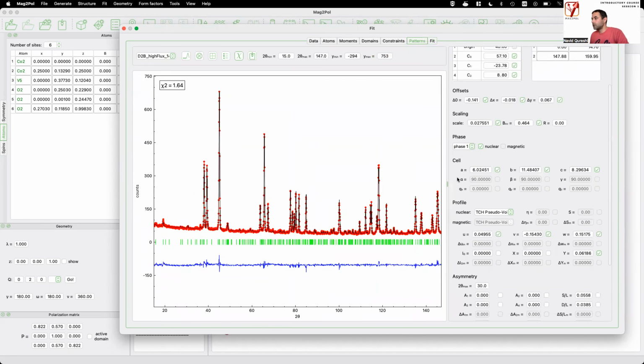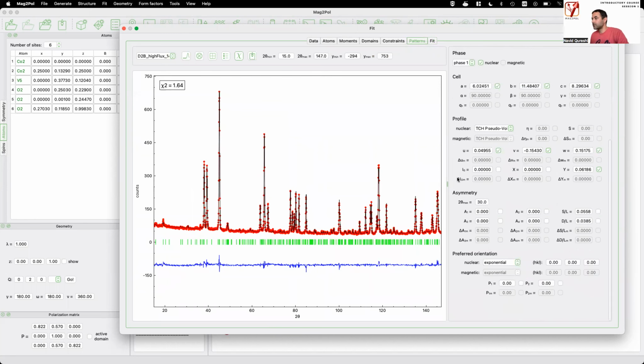There's one detail I haven't mentioned, and there's probably one person in the audience who has asked me this question. That's concerning the asymmetry. Apparently these parameters, the sample height over distance and detector height over distance, may cause some trouble with other programs. So it's just to show you that it works like a charm with Mag2Pol. The asymmetry is applied up to a scattering angle of 30 degrees, but you will see here that up to 30 degrees, we don't have much information. So it wouldn't make any sense to refine those parameters like this.